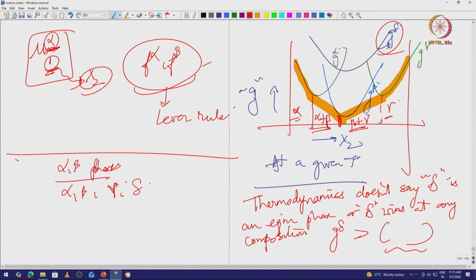So, a very slow process for a long time and then I let the system stabilize, give enough time and temperature for the diffusion kinetics to happen, right. So, then depending on composition range, thermodynamics just says that if you do this long enough, according to thermodynamics the equilibrium phases are alpha, alpha plus beta, beta plus gamma, gamma, these are the most stable phases, right.